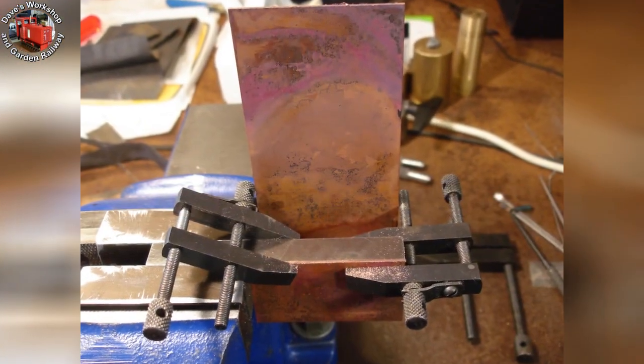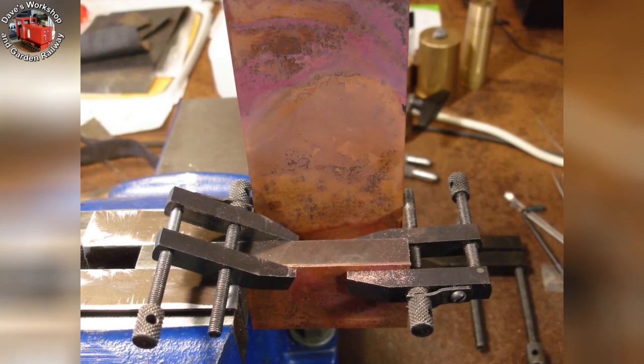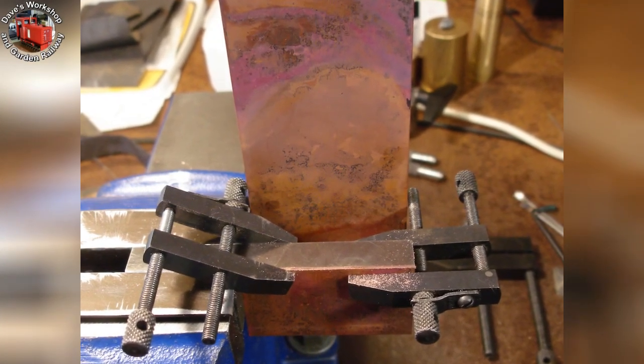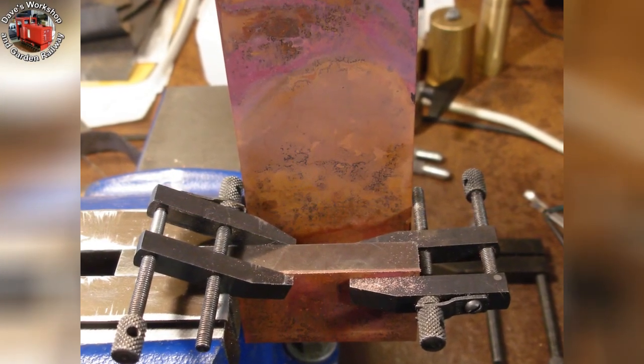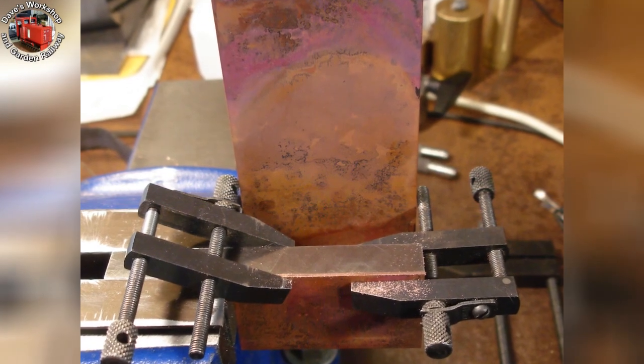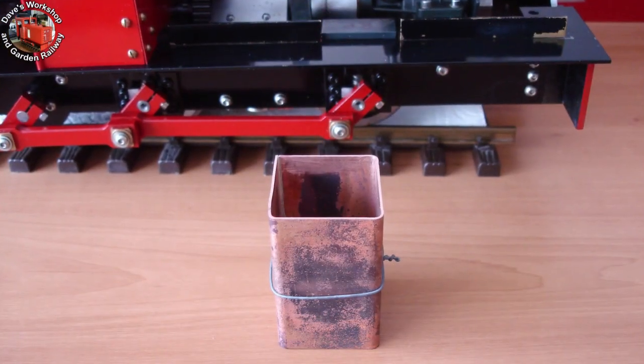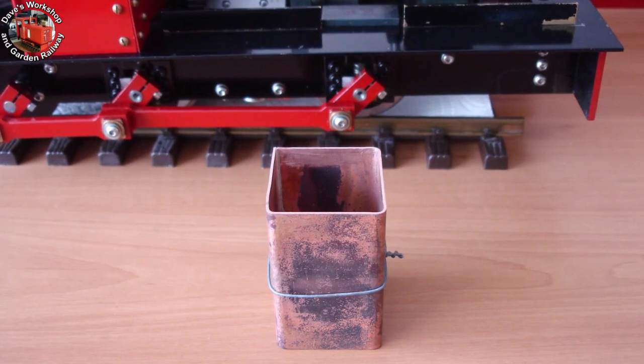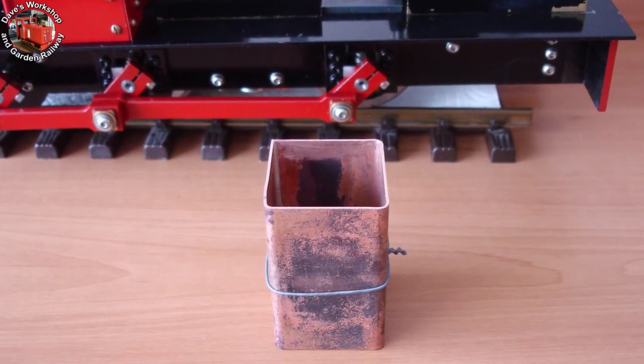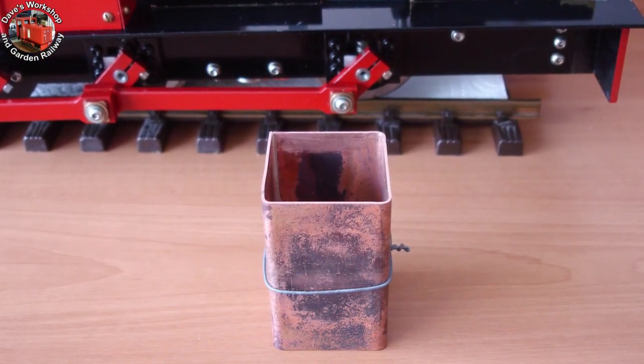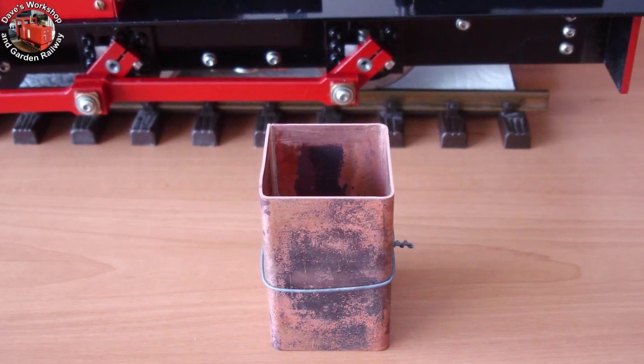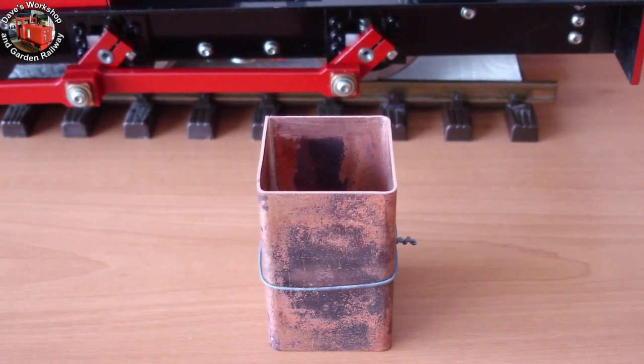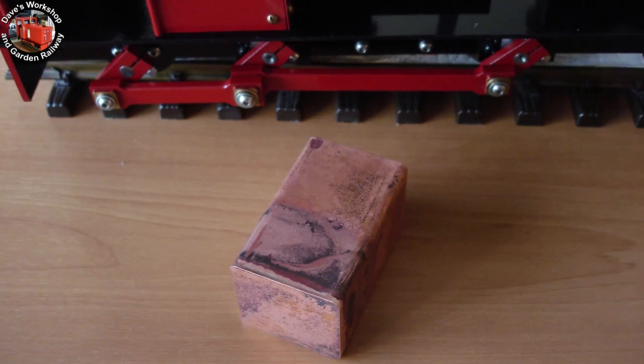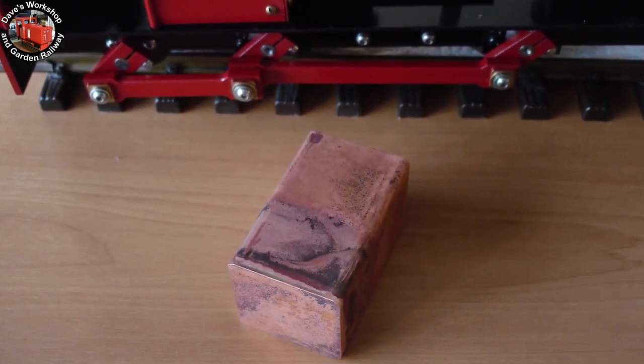Partially bent after annealing. I'm just filing the first bent length to get the correct dimension, using a piece of 1/2" tool steel as a filing guide. Here's the tank shell silver brazed for security, wired tight for subsequent brazing of the first end plate. The dimensions should be 38mm high, 40mm wide and 61.2mm long. End plate brazed on and filed to size afterwards.